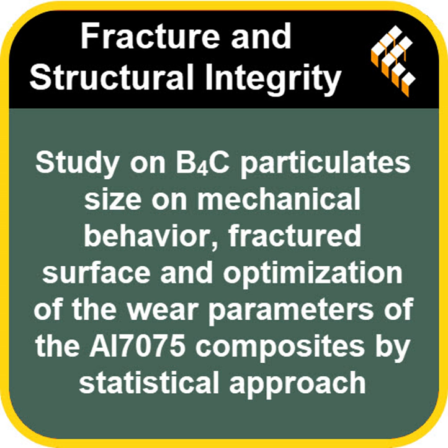And why such severe wear for micro? It's likely due to higher strain levels right at the particle interface, that stress concentration we talked about, weaker bonding between the big particles and the matrix. All this can cause the matrix material to crack or the particles themselves to break or get dislodged. You end up with these irregular wear tracks and much more material flying off. It really highlights the dramatic difference in how these materials fail under wear.